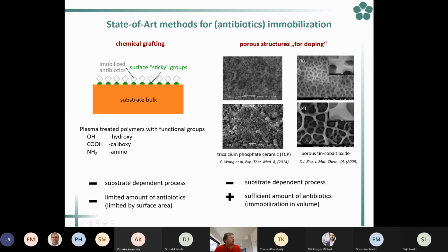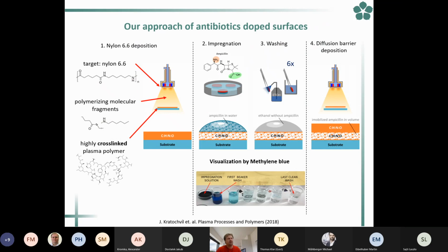And here are already quite known approaches using, for example, tricalcium phosphate or some metal films that are porous, where the molecules can be impregnated. In our case, we were dealing with a different approach. By the plasma, we were able to deposit plasma polymerized nylon by the sputtering of a nylon target. So practically, we have the nylon target igniting the plasma. We are able to sputter it, but we sputter just only some fragments of this monomer